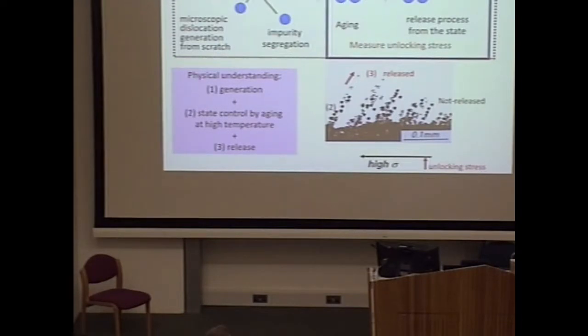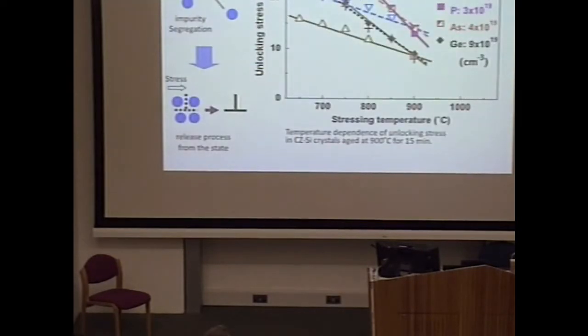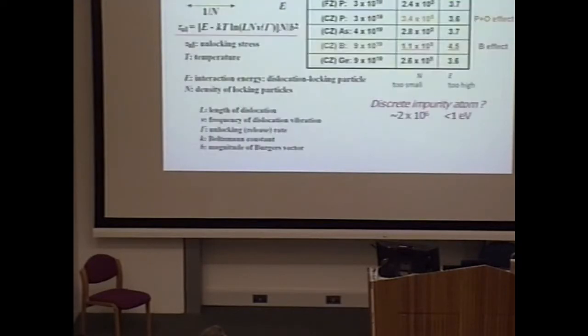So by this method, we measure the unlocking stresses. So this is the relation between the unlocking stress and the stressing temperature. So dislocations aged at 900 degrees C for 15 minutes, a very short time, but dislocations are quickly locked by impurities. So this kind of unlocking stress depends on the stressing temperatures. And by this linear relation, it can be analyzed by using this equation. So this is the unlocking stress, and also here.